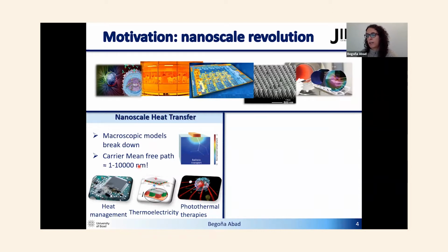So for dielectrics and semiconductors, the main carrier is a phonon, and the phonon mean-free path can range from 1 nanometer to even 10 microns. So it's really easy to achieve these features on the order of the phonon mean-free path. And this is not only important from a fundamental point of view, but it also has technological applications like heat management,